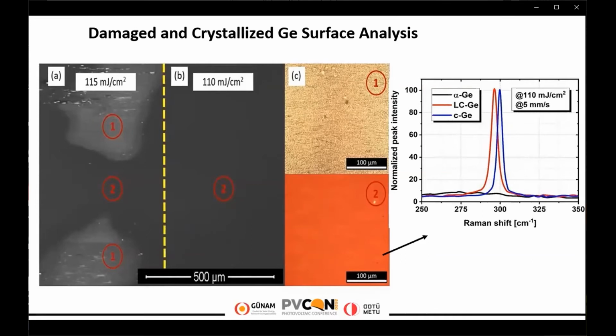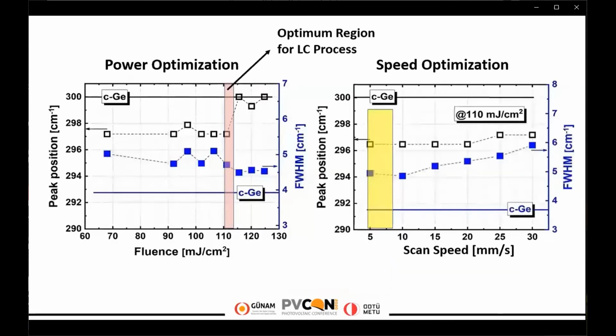And Raman shift of crystallized germanium and bulk crystal germanium are compared. And Raman shift of crystallized germanium is very close to Raman shift of bulk crystal germanium. And in order to determine the optimized laser fluence, we scan sample with different laser fluences. And for laser fluence lower than 110 millijoule per centimeter square, the line width of Raman shift gets larger because of high density of defects or crystalline size.